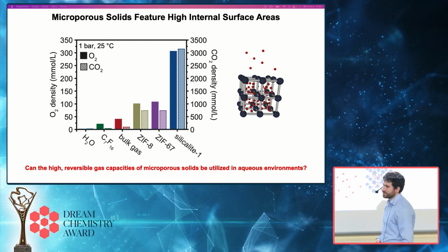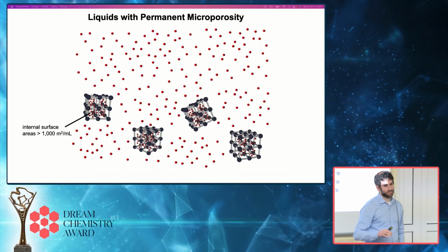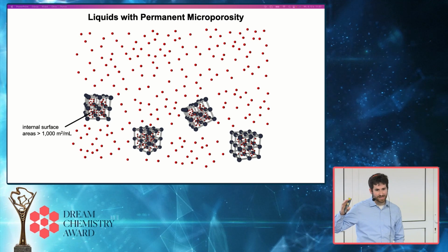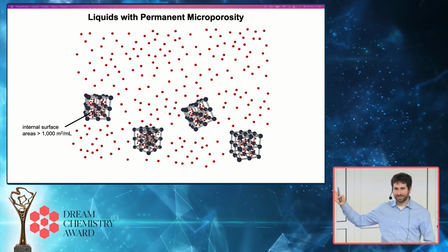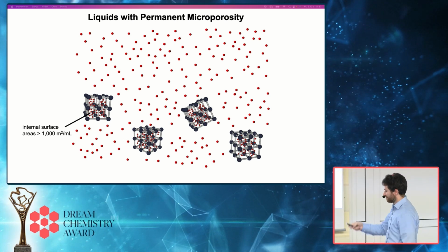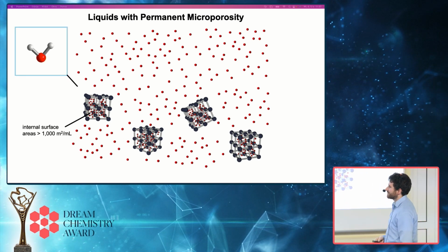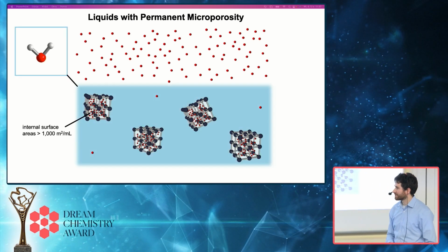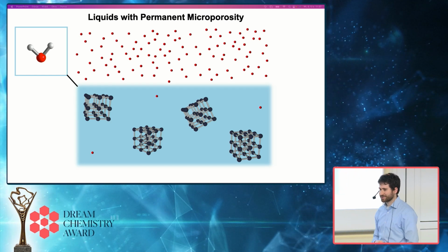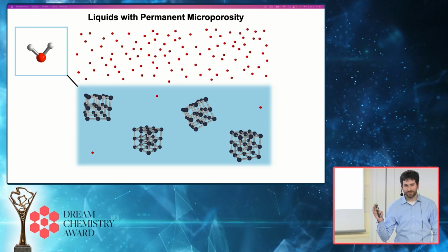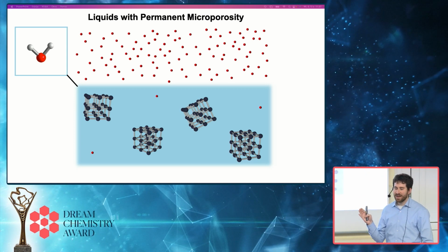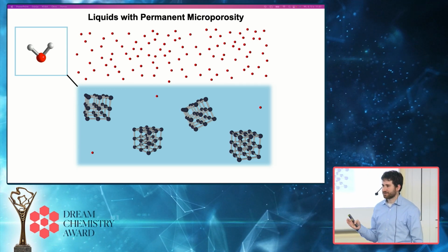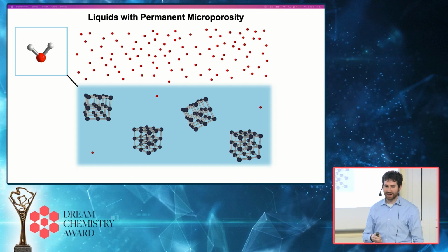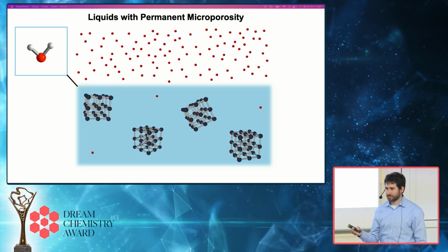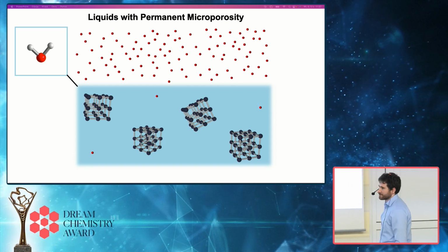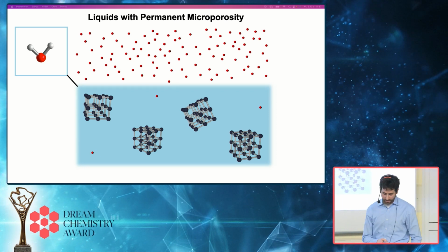So the problem that you run into if you want to think about doing this is as soon as you take most microporous solid materials that again have really high internal surface areas, really good at absorbing gas molecules, as soon as you put them in water, water will tend to fill those pores, right? Water is going to be smaller than most gas molecules that you would want to absorb. You flood the pores, you remove all of this internal surface area, and you wind up generally with an aqueous solution that actually dissolves less gas than if you didn't have the porous material present. And so most porous materials are not actually that useful for transporting gases in water.